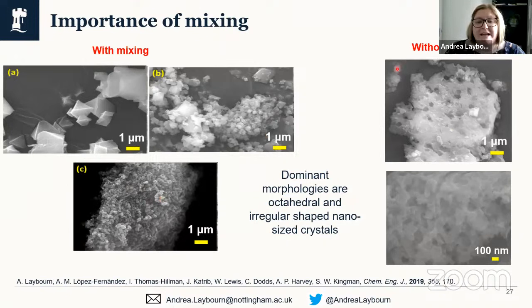Now, if we turned off the oscillation and just had a net flow, so we'd reduce the amount of mixing that you would get, what we saw was that we produced materials which were fused together. So you can see that these are not discrete particles which have agglomerated, such as shown on the left-hand side. We've got materials where the particles have fused together. And so if your application is such that you want to be producing a free-flowing powder or discrete particles, then you will definitely be wanting to have mixing within your reactor.